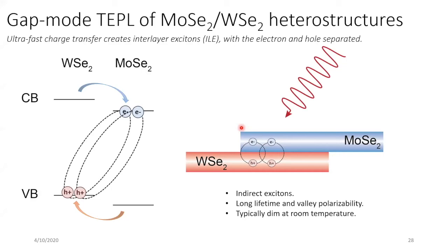These differ in a couple of important ways from the normal intralayer excitons. They tend to be indirect because they're still at the K points inside the Brillouin zone and usually have some lattice mismatch or maybe some twist angle. They're momentum indirect. They're spatially separated, so they have a permanent static dipole moment. There's not as much overlap between the electron and hole wave functions. They're not as radiatively active, lower oscillator strength. So they have corresponding longer lifetimes. The presence of the static dipole plus longer lifetimes has a lot of people excited because you might be able to observe very interesting phenomena like Bose-Einstein condensation.